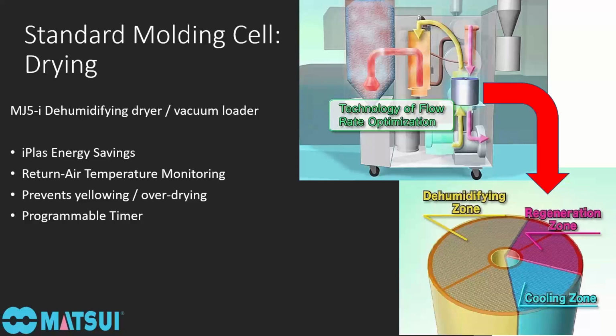So that can lead to energy savings because it's drying the same amount of material but with a smaller unit. So the overall kilowatts of the heater and blowers will be smaller. Also, the footprint will be smaller. Say you want to dry 100 pounds per hour of ABS. Instead of needing 4 hours to dry it and having to have a 400-pound drying hopper, the MJ5i can dry it in 2 hours and would only need a 200-pound drying hopper. So the physical size of the unit will be much smaller, which is important when using it in an injection molding machine cell beside the press.